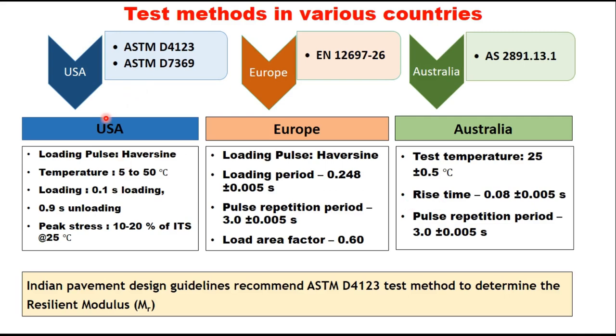One is the US method given in ASTM code, another is the European method given in European code EN 12697, and the third is the Australian method given in AS2891. In all three methods, the loading pulse is haversine. The only difference is the loading period and rest period.